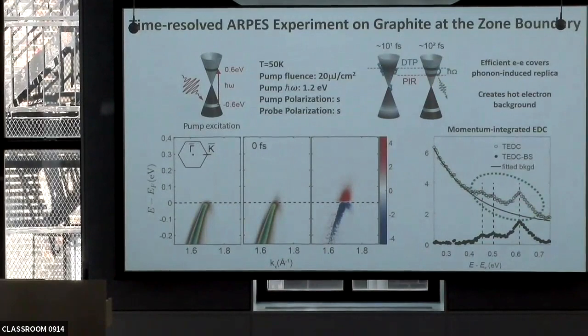And so to some, this peak at 0.6 is precisely what we expected to be able to see. We see some structure that perhaps is suggestive of this phonon relaxation mode. But in fact, there is more than we expected. And we also see that there is a tail, and the tail is really due to the electron-electron scattering, which is very fast, and so it's dominating. And we'll then take the intensity from this value to something which is 4 orders of magnitude higher.